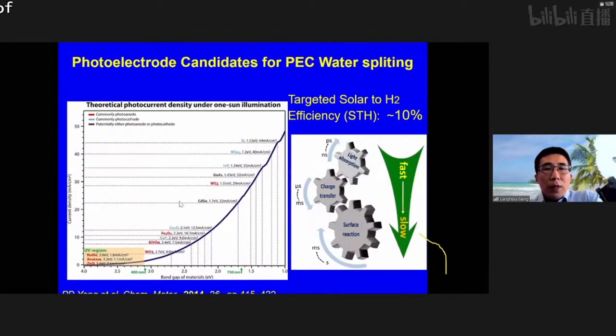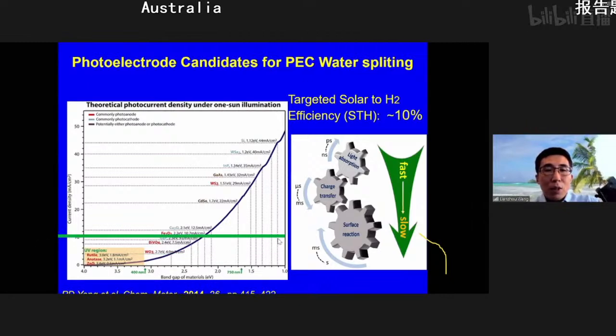So, if you look at this chart, in terms of the candidates, as I mentioned, the photoanode is now the bottleneck, and it's highlighted in red. And you can see that most of the available photoanodes have relatively low photocurrent. This can be translated to the solar-to-hydrogen efficiency. And if you really want to target a solar-to-hydrogen efficiency of 10%, basically we need to reach around this level.